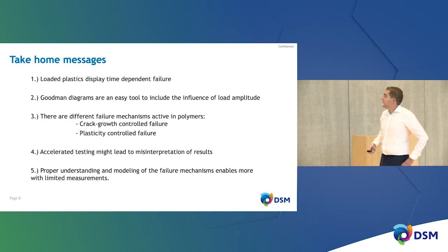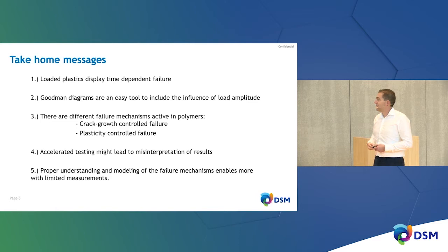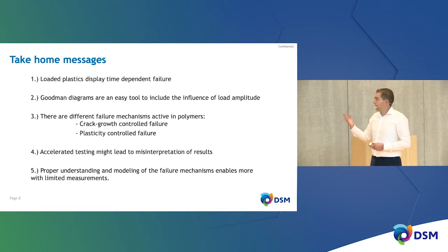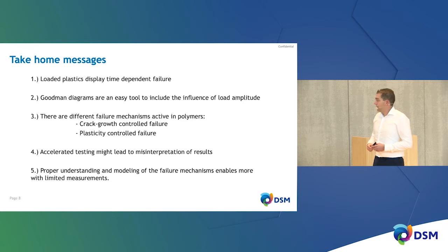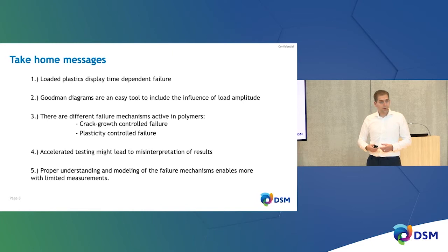I want to start with some take-home messages. First: loaded plastics will display time-dependent failure. Goodman diagrams are an easy tool to include the influence of load amplitude or mean stress sensitivity. There are different failure mechanisms to consider — crack-growth controlled failure and plasticity-controlled failure. Accelerated testing might lead to misinterpretation of results. And if you understand the failure mechanisms, you can model them, enabling more accurate predictions and more with fewer experiments.